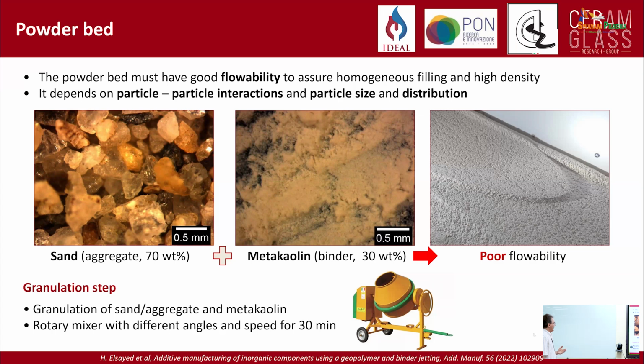So 30% of metakaolin binder. If you try to print it mixing it with sand, you obtain a particle bed that contains a lot of defects. And of course, all these defects will be present in the final part, reducing the strength. So what we did was to follow a granulation step using just a concrete mixer. We are able to coat particle sands with a layer of metakaolin. And in this way, we have coarse particles coated with the reactive particles that are loosely attached to the aggregate. And this allows us to spread an even powder bed.